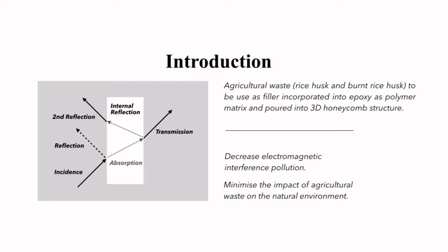So, this is the diagram which shows how the absorption phenomenon occurs. The white rectangle represents the absorber. When incident rays hit the absorber, some will be reflected and some will be absorbed into the absorber. A good electromagnetic wave absorber is one that has lower energy dissipated from the reflected wave, as more energy has been absorbed by the absorbing materials.